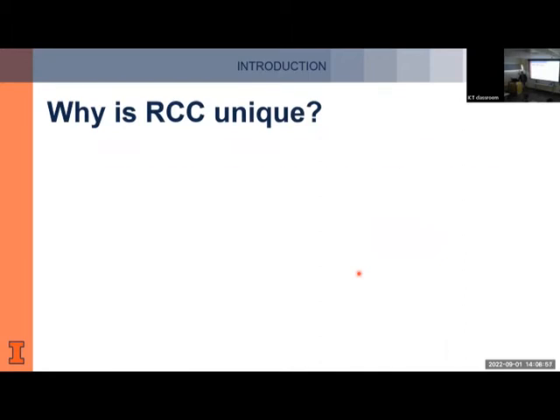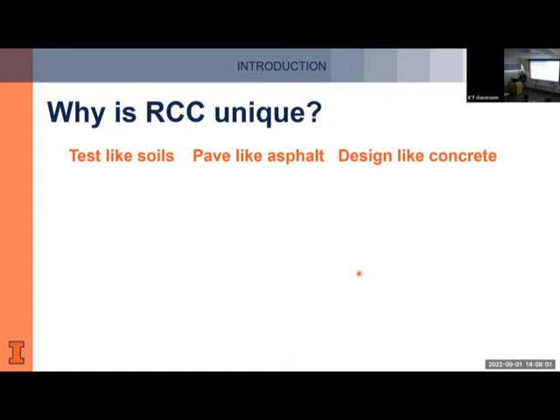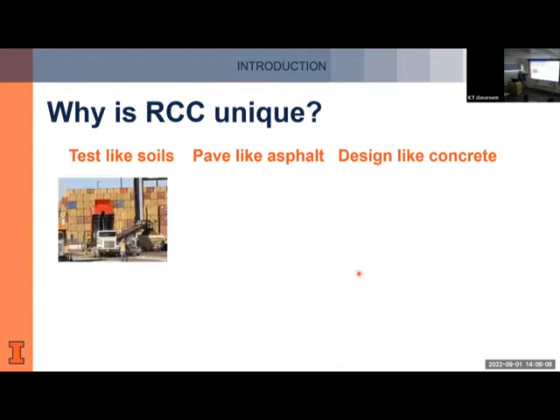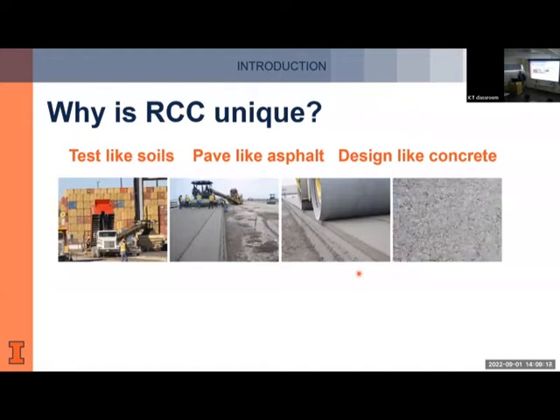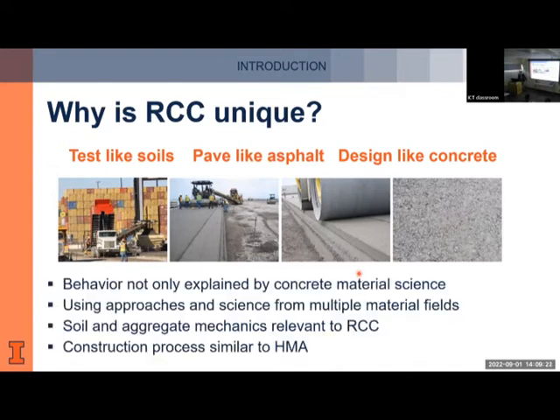Why is RCC unique? It's tested like soils, paved like asphalt, and designed like concrete. You transport it with dump trucks, pave it with a paver like asphalt, roll it like you would roll a granular base or an HMA pavement, and then design it once hardened like a concrete pavement. The behavior is not only explained by concrete material science — you can't assume it has the same properties as conventional concrete. Approaches from soils and aggregate mechanics, including concepts like pore water pressure and effective stress, are all relevant to RCC.